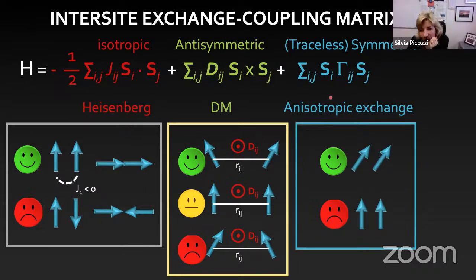This anisotropic exchange will actually do what? It will also tend to align the spins along a certain direction. So people sometimes call it two-site anisotropy. So they want to have a certain direction. It's not single-ion anisotropy, but it's like two-ion anisotropy, but it still favors the alignment of the spins along a certain direction.